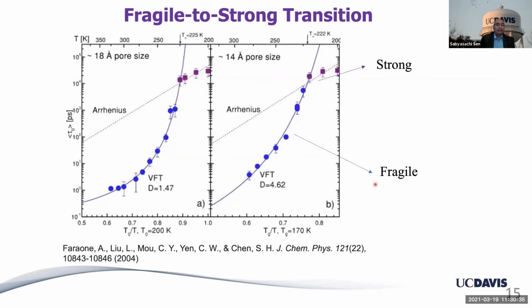Now, we think that this provides a direct explanation of this long-standing puzzle in the water behavior in nanopores in the literature. This is just one of the many papers that have been published over the years showing that if you plot the time scale of water dynamics, in many cases measured by dielectric relaxation, let's say, or neutron, in an 18 angstrom pore and a 14 angstrom pore, both show pretty similar behavior: that the relaxation time or the dynamical time scale is strongly non-Arrhenius, meaning the activation energy is strongly temperature dependent at slightly